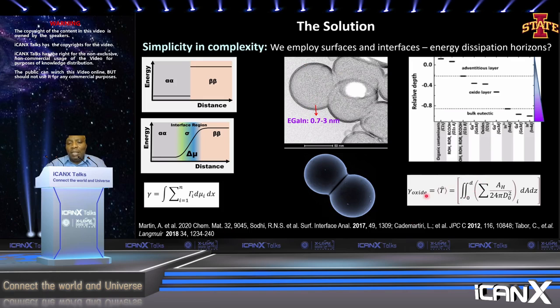And when you see something like this multidimensional component, it means that thermodynamically, I can engineer this by playing around with the distributional component at the interface to allow me to do something that will affect the bulk of that material. And if I reduce the size enough, I can get to a point where this oxide will actually play a significant role in how the bulk material behaves.